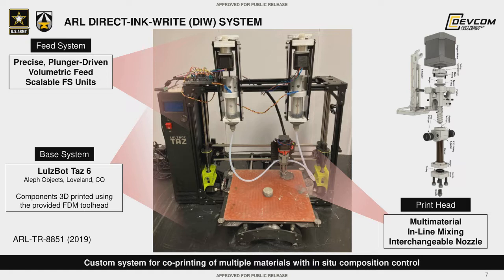So going in order, the workhorse of our direct ink write work has been this Lulzbot direct ink write system that was developed by Dr. Nicholas Koo and Joshua Pelz at University of California, San Diego. What this is essentially is an off-the-shelf fused filament fabrication printer that we've hacked and modified in order to work with aqueous ceramic ink suspensions that we developed ourselves in-house. So instead of the filament, we have two precise plunger-driven volumetric feed units that feed into an inline auger, which mixes the two inks at a ratio that is programmable within the software, and then extrudes it out into the parts as controlled by the design software inside the printer itself.